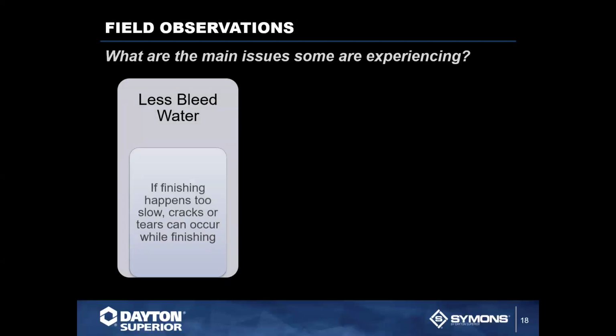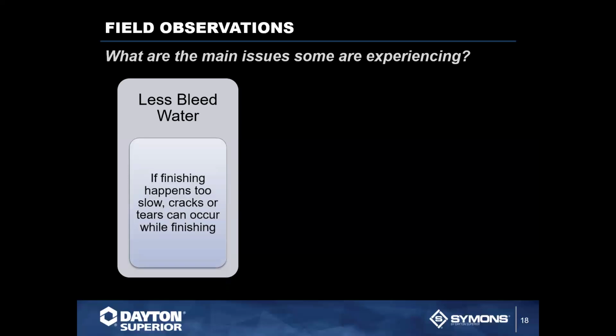So the problem that we're seeing on sites with the type 1L, you got less bleed water. Limestone is very porous and it sucks up a lot of moisture. So it basically is going to help suck up a lot of that bleed water that you typically thought you'd have. So you're going to have to be very conscientious of whether cracks, tears can occur while you're finishing it. You don't want to over finish it or burn it with your trowel.